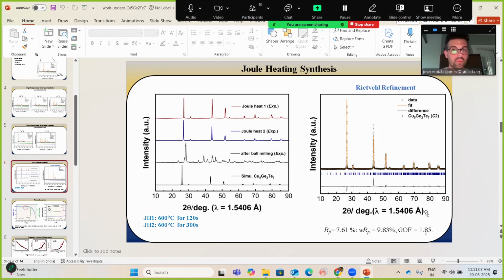In fact, I can see which samples Chengguang prepared, because the sample displacement is different. So from person to person it is very, very constant. So if Jayant has done these experiments, it's too large to be a systematic error, I think. Unless the samples were prepared completely differently, it's odd.